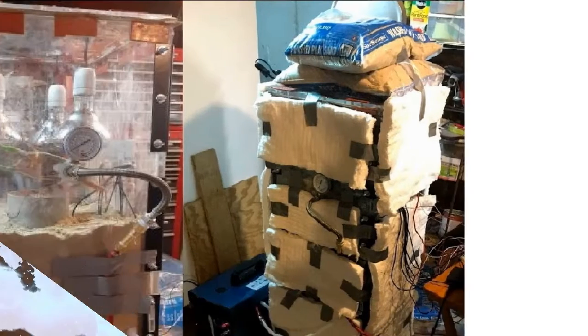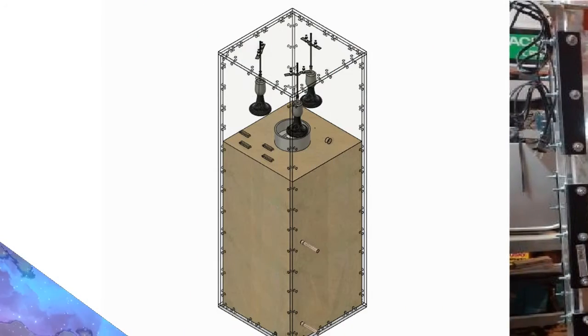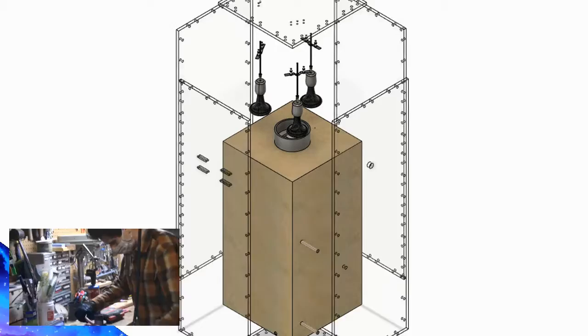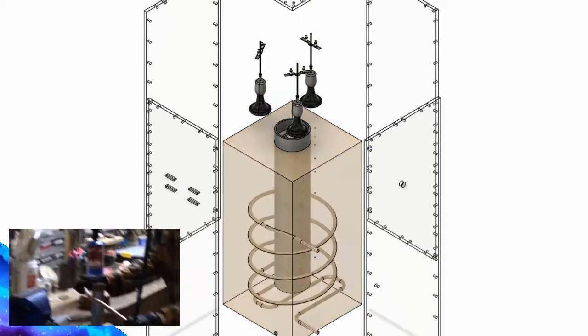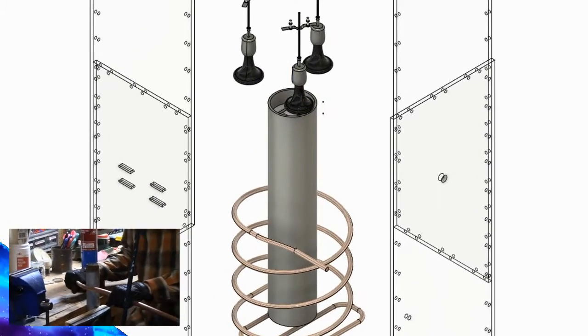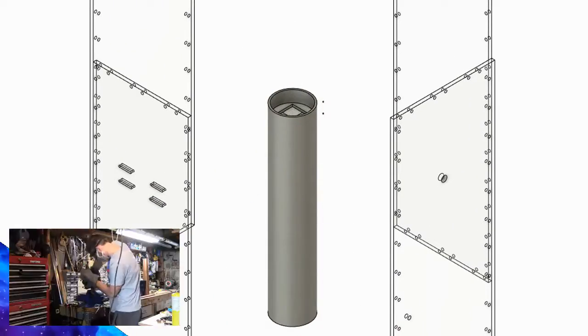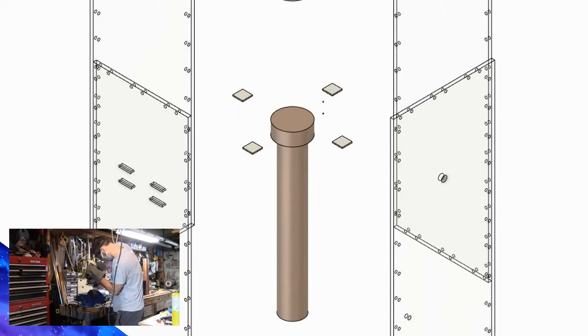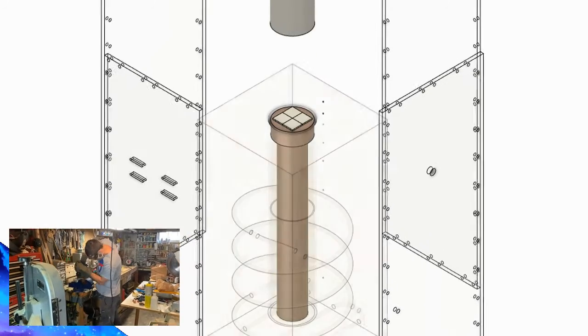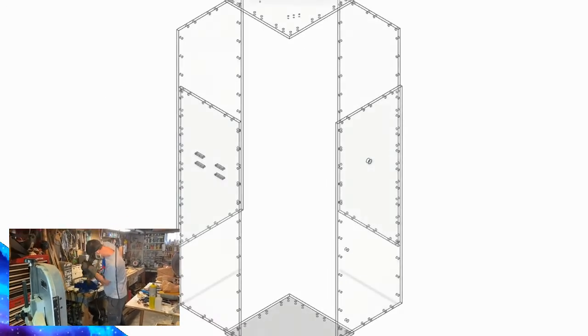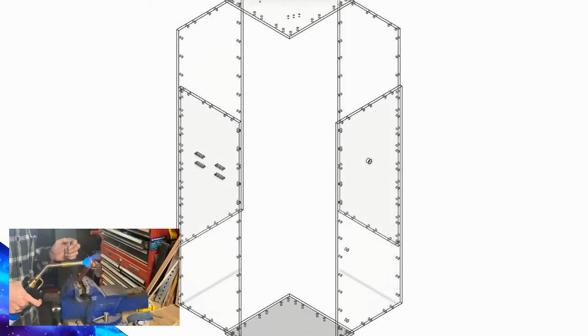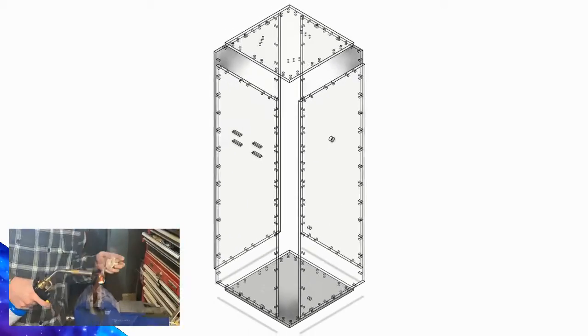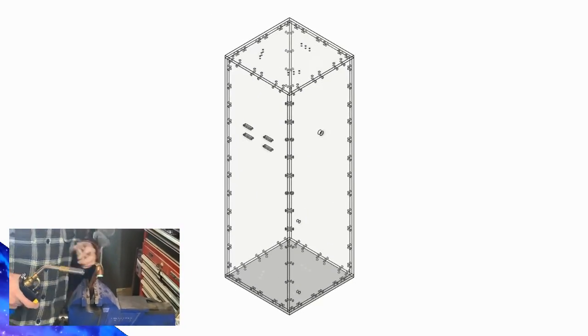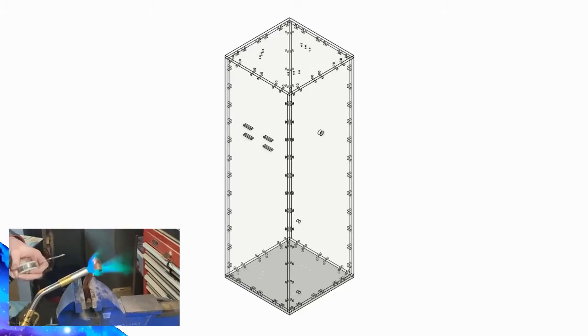The test rig is a vacuum chamber with surface heating and subsurface cooling systems that simulates a lunar thermal environment for the experimental testing of our mock thermoelectric helical anchor prototype. To simulate the lunar surface's thermodynamic behavior, the experiment was performed in a near vacuum. To achieve this, we made a vacuum chamber with half-inch acrylic sheets. The vacuum chamber is held together with acrylic cement and 16 steel brackets with O-ring sealed bolts and is sealed with silicone.